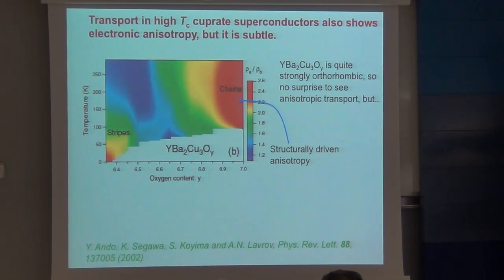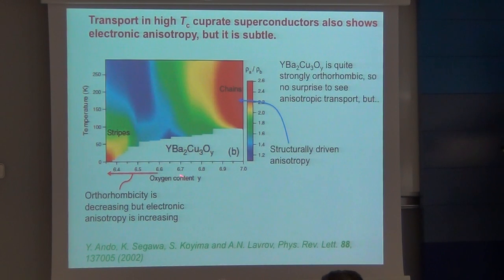But what Ando pointed out was that they could carefully make these superconductors with different oxygen content, and as they made the oxygen content smaller, the level of orthorhombicity went down, but they reached a level at low doping where the thing was almost tetragonal structurally, but the anisotropy came back. So their argument was that you would find static stripes.